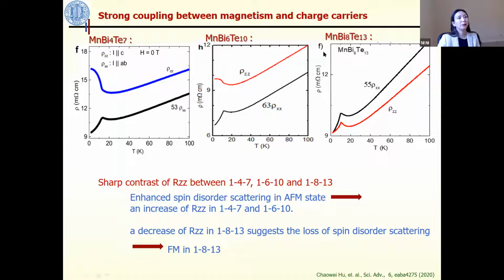aligned, right? So if you look at 1-8-13, even for those ZZ, in the ordered state, the resistivity actually drops. So this is a second evidence saying that in the 1-8-13, along the C-axis, the spins are aligned parallel with each other, and along the AB plane, the spins are aligned parallel with each other. So both the magnetization measurement and the transport measurement suggest that we have a ferromagnetic compound here.